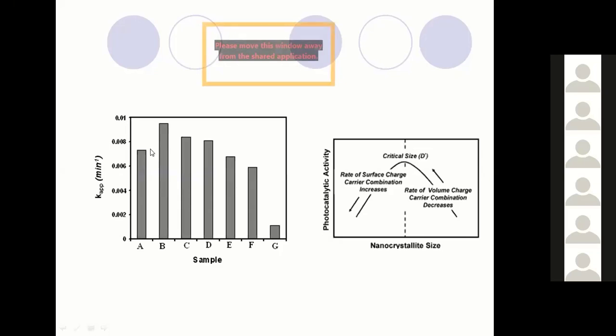But when we go further beyond this 5.5 nanometer size to 2 nanometer, again the photocatalytic activity was decreasing. So here you can conclude that there is a critical size for every property. If we go beyond that critical size, the property will not be as smart. With the decrease in the particle size, photocatalytic activity was enhancing up to the critical size.